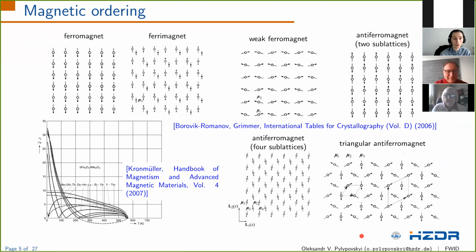Such a complex intrinsic structure of media, shown at the right-hand side, determines the complex and interesting behavior of these materials from both fundamental and applied points of view. Depending on the number of sublattices, it's possible to introduce a few vector order parameters to describe the microscopic state of an antiferromagnet. Usually, we are interested in some anisotropic and chiral properties of the media to utilize them for practical purposes. They are determined by the local crystalline surrounding of the magnetic ions. By fine-tuning of their combinations, as well as utilizing magnetic multilayer structures, it's possible to obtain the desired properties in some temperature range. This can be illustrated by the large family of the rare earth garnets, where, for example, the substitution of the conjugate ion changes the compensation temperature point. This tunes the saturation magnetization and behavior of magnetic textures.